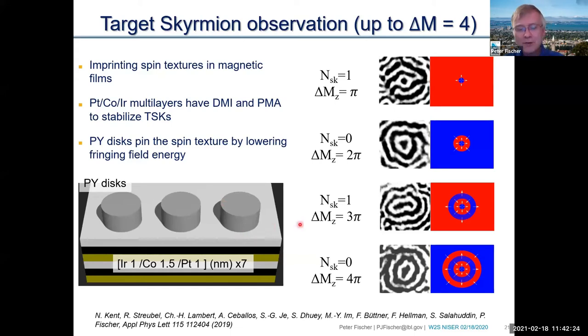Now I also have to say that it was possible to image those because we used the elemental specificity at the cobalt edge. Permalloy, nickel iron, doesn't have any cobalt, but we were able to look through the permalloy disc just underneath without taking it apart. So this, I think, was a unique capability of X-ray microscopy, to look through a permalloy disc that is about 50 nanometers thick onto the underlying cobalt platinum iridium disc. And we were able to see that right underneath this disc, we did see these target skyrmions.